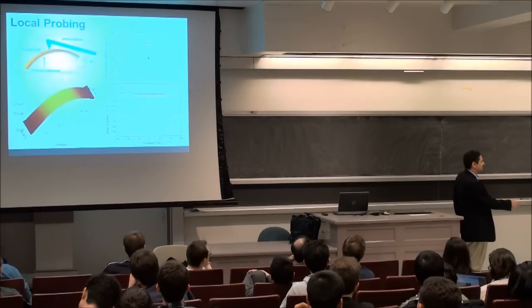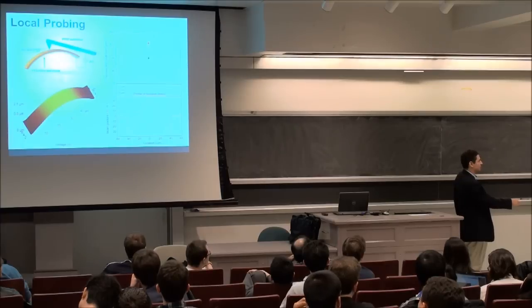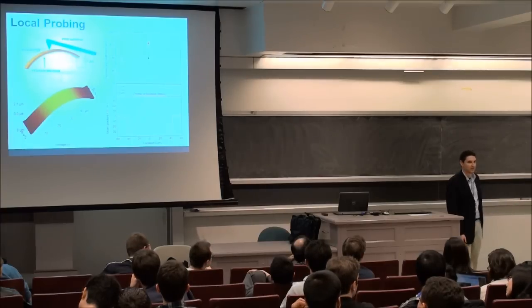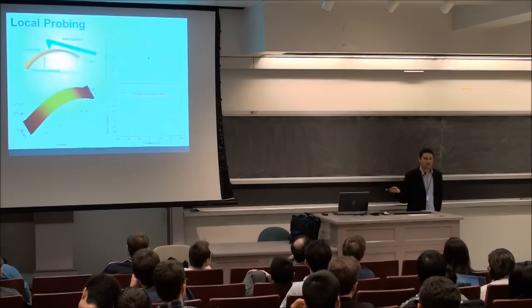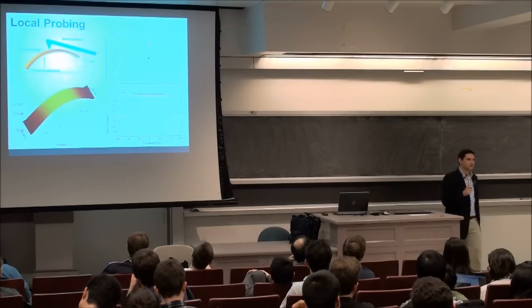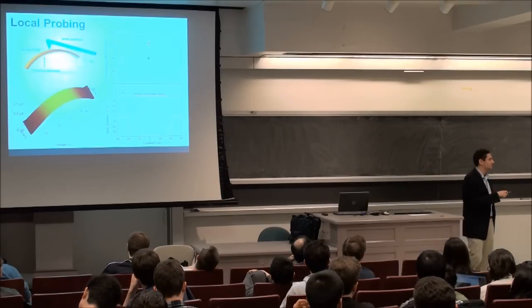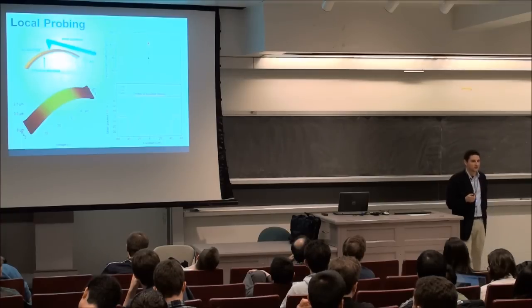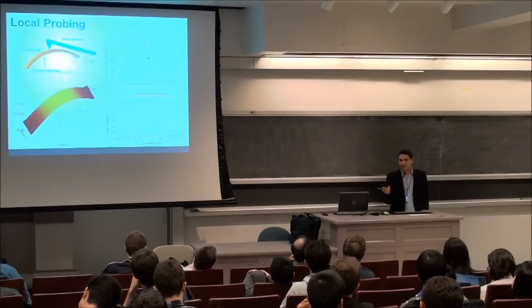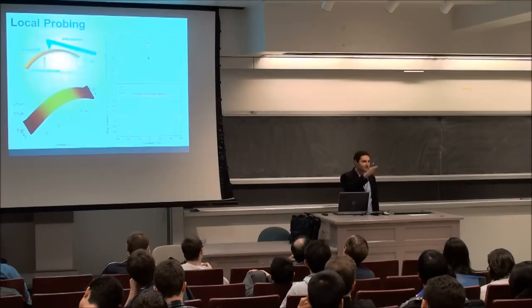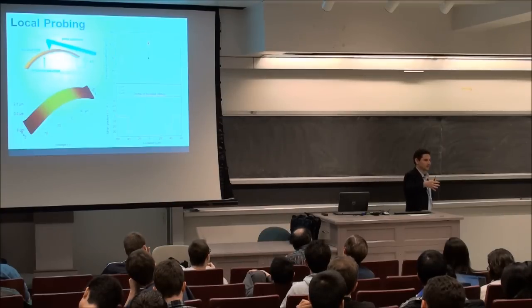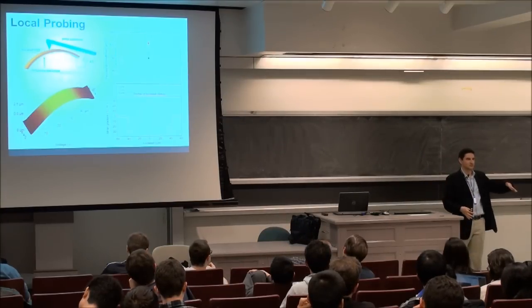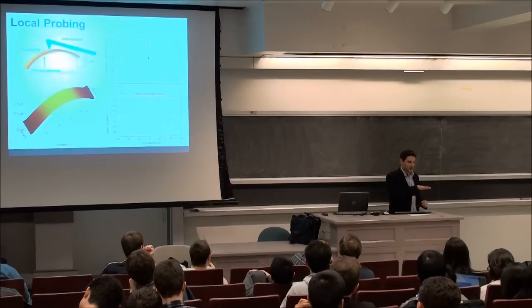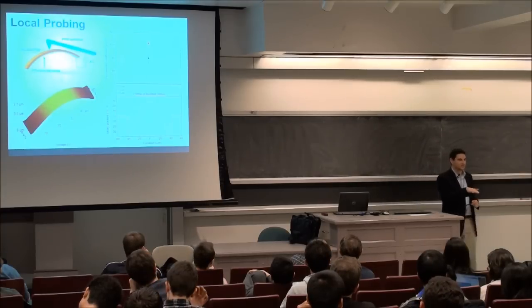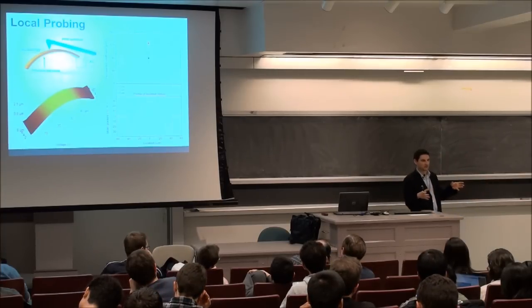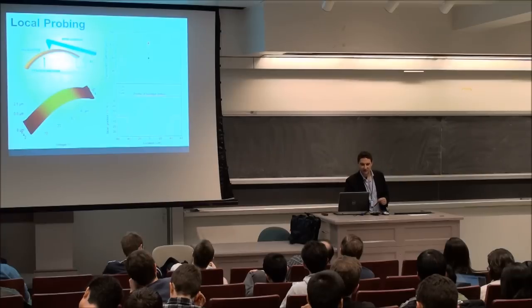Okay, here's a calculation of the strain gradient as you go along the ribbon there. This is the profile of the buckle there. So one of the things we've been studying a lot these days is trying to figure out where this increased piezoelectric response comes from. Okay, there's basically two things that we can think of. The first thing is that the buckle is off the substrate. It actually comes off of the substrate, and so as a result, it's not clamped by the substrate underneath. It's not damped. The substrate is basically this elastomer, so it acts as a damping force or damping energy.